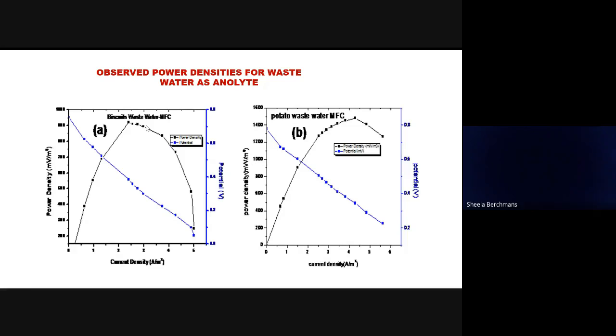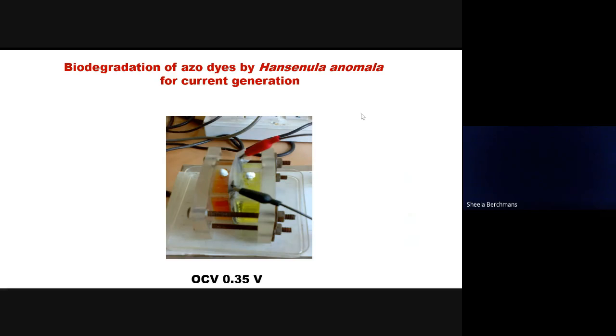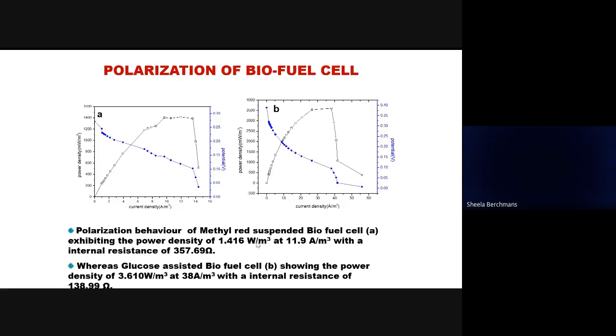We used two different types of wastewater, biscuit factory wastewater and potato chips making wastewater. Here 1.4 watt per meter cube of power could be produced by making use of this waste. Also, we tried to degrade azo dyes using Hansenula anomala for current generation. This is a dye-based microbial fuel cell which we developed in our lab, where we used the azo dye methyl red for the generation of electrical energy. Using this, 1.416 watt per meter cube could be produced at 11.9 ampere per meter cube, and the internal resistance was